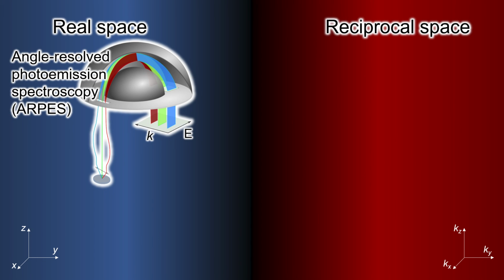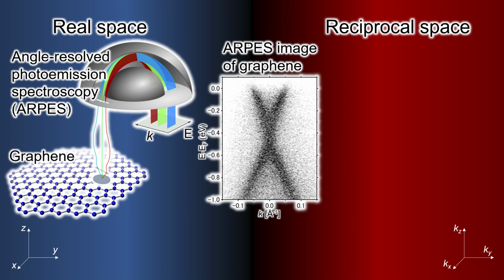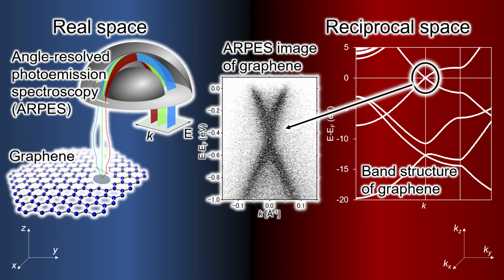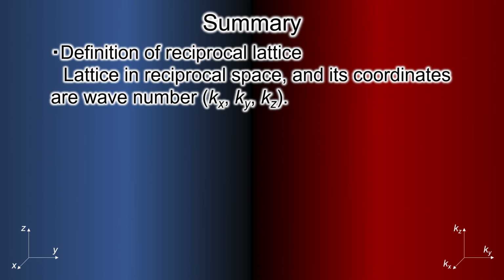Such an energy band structure can be directly observed by a measurement called angle-resolved photoemission spectroscopy. Here is the experimental result of a graphene sample, which is a two-dimensional material. It is similar to the band structure obtained by calculation. The slope of the band at Fermi energy, 0 electron volt, is called Fermi velocity. If you calculate the Fermi velocity from the experimental results, it is about 1000 km per second. Thus, by examining the energy of electrons in the reciprocal space, we can understand the characteristics of the material. Here, we focused only on the electronic state, but states such as vibration in a solid have a similar dispersion relation.